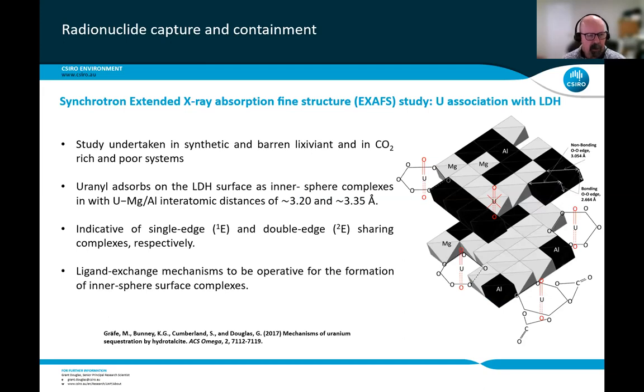And now we're looking at some other work we did on the synchrotron using XAFS. This was a study using both synthetic and barren lixiviant and in CO2 rich and CO2 poor systems. Now, all I really want to talk about in this slide is that we were able to show that rather than uranium being accommodated within the metal hydroxide layers per se, they were actually all accommodated on the edges.